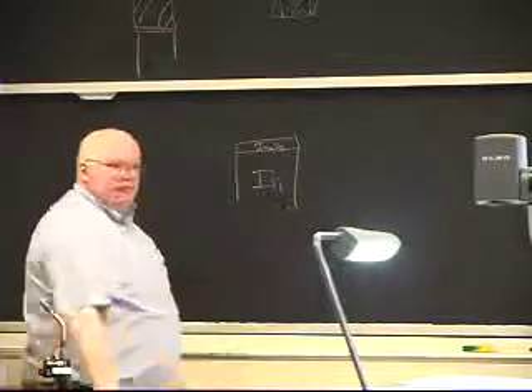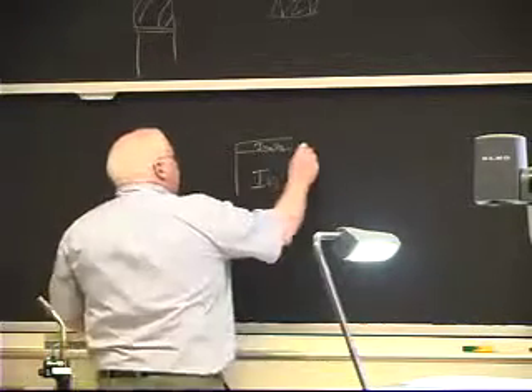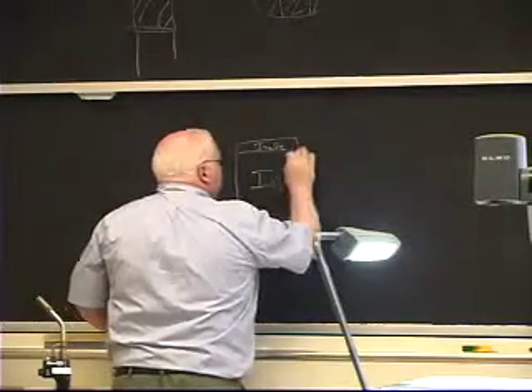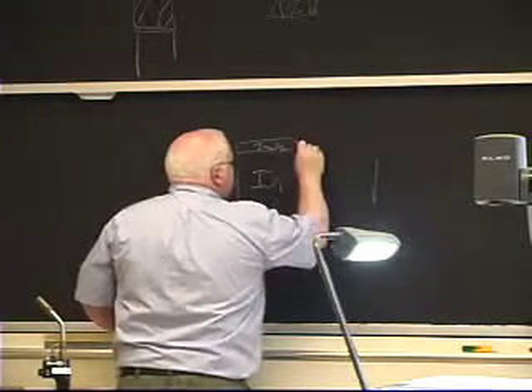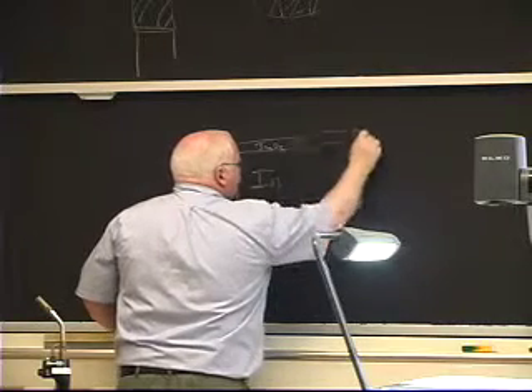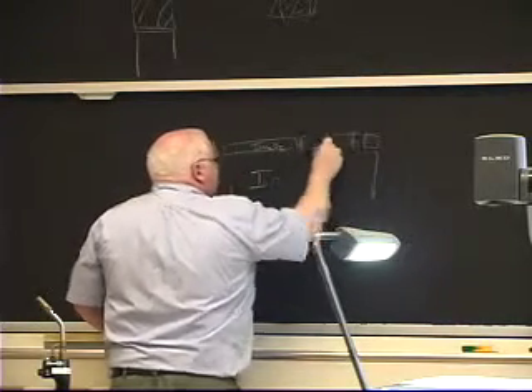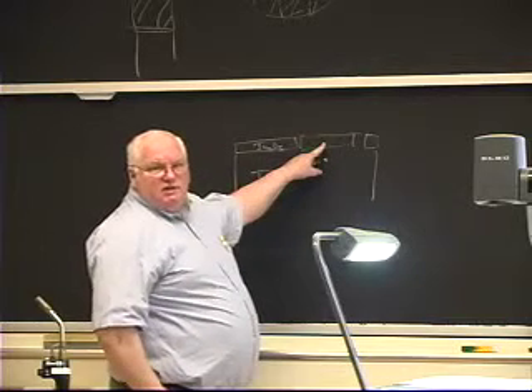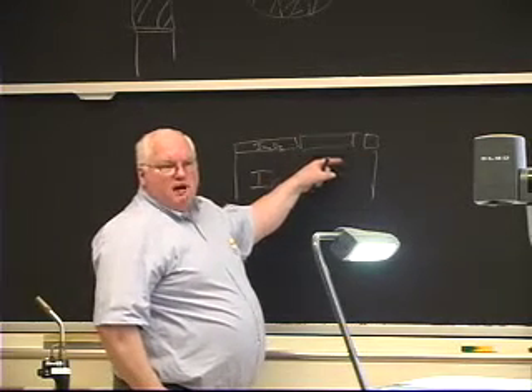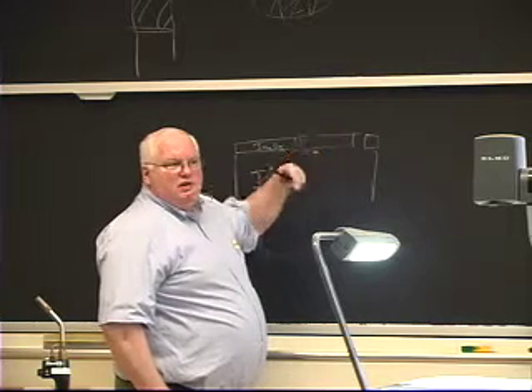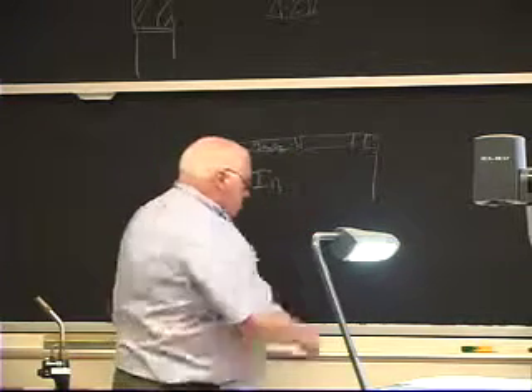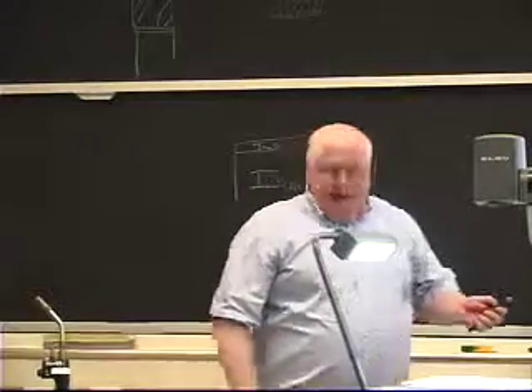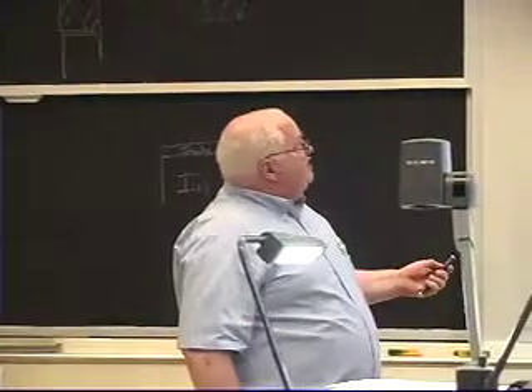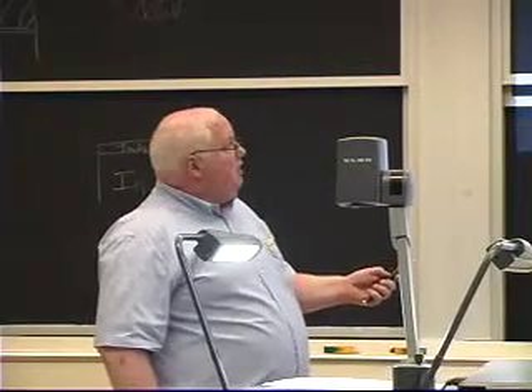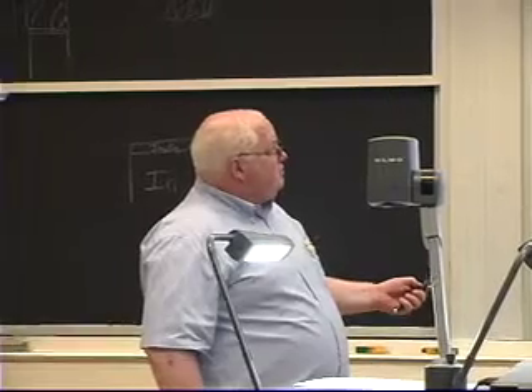Indium is softer than lead, okay? But I need to break up that oxide on the surface. I need to crack it and move it away. And the softer the oxide is, the more it's just going to smear and fill in the cracks. The harder the oxide, the easier it is to break it up, to get a decent bond. And it turns out, by doing tests, indium has by far the highest oxide to metal hardness ratio, in part because it's such a soft metal, okay, but it also has an oxide that has the same crystal structure as aluminum.